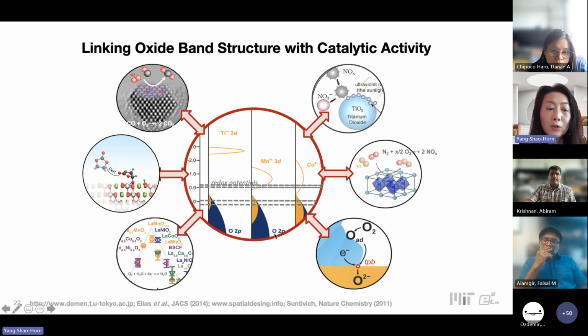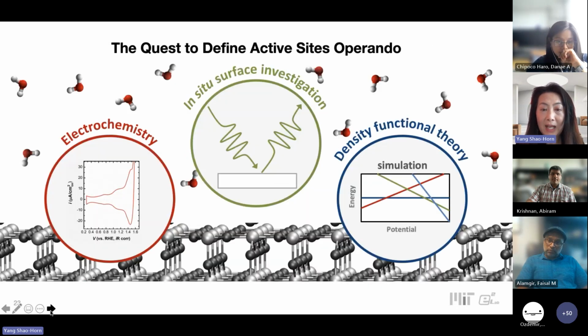Right. So we developed an approach where, instead of studying different reactions independently, we utilize a holistic approach: tuning the active sites or binding of the metal sites, as well as tuning the oxygen sites, so that the oxygen site has the right binding energy to absorb or dissociate various bonds in order to increase the rate of the reactions. And you can see that in these contexts, we can think of electrochemical reactions as well as chemical reactions. Basically, the principle can be very similar: utilizing electronic structure and surface binding to weaken internal interactions to facilitate the rate of the reactions.